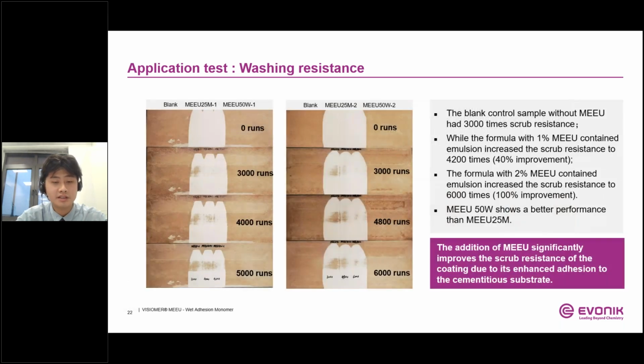Look at this picture. The left is the blank control sample, and MEU25M-1 represents 1% MEU25M emulsion used in the formulation, and the same with the 50W. And this picture in the middle is the dosage 2%. It can be seen that the number of scrubs are significantly improved after the addition of MEU monomer.